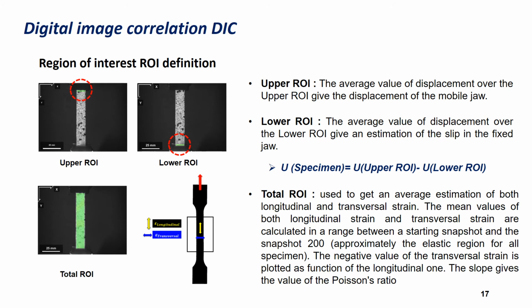Then, a large region of interest is defined to get an average estimation of both longitudinal and transversal strain, and therefore allows the calculation of the Poisson ratio. Using DIC avoids the problems of placing a strain gauge on the surface of the 3D printed specimen, since the surface is not perfectly flat and delamination of filaments is possible.